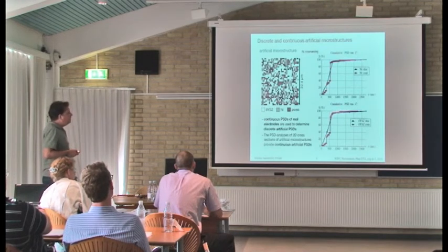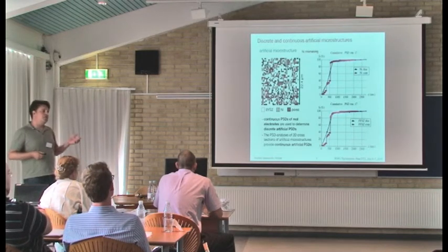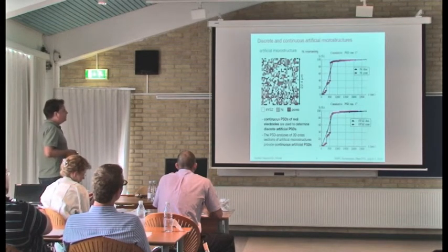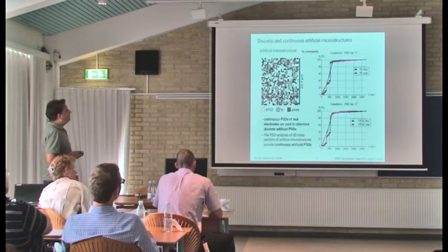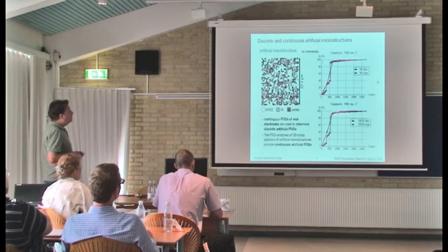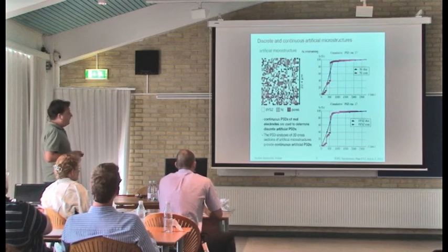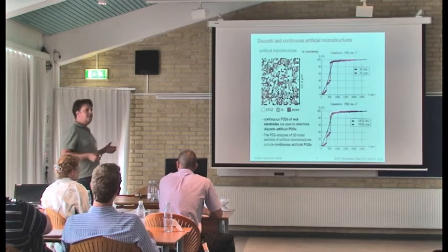I start out with a continuous particle size distribution as I get it from Lorentz Holzer for a certain real electrode, and then I assume that my discrete particles have the same PSD. This is represented here for the nickel phase by this blue curve, the cumulative size distribution of it. So to say, I'm here still at the stage where I have my single particles.